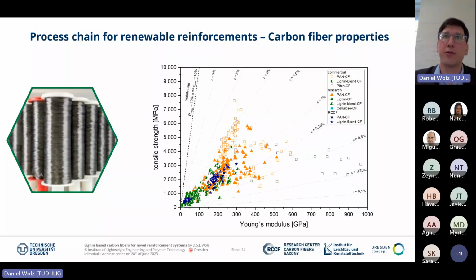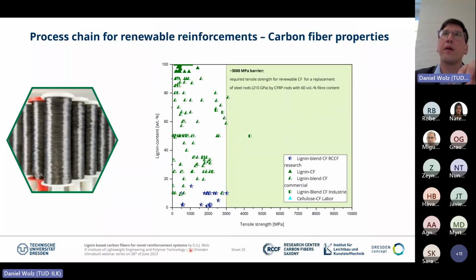Meaning, if we are looking into the requirements for CF reinforcement rods, then we have additional challenges to do. For instance, if we would like to replace a steel rod with 210 gigapascal tensile modulus by a CF reinforced polymer rod with 60 volume percent fiber content, we would need a tensile strength barrier of 3000 megapascal to challenge. This is already achieved by lignin blend fibers with 50 to 80% lignin content.